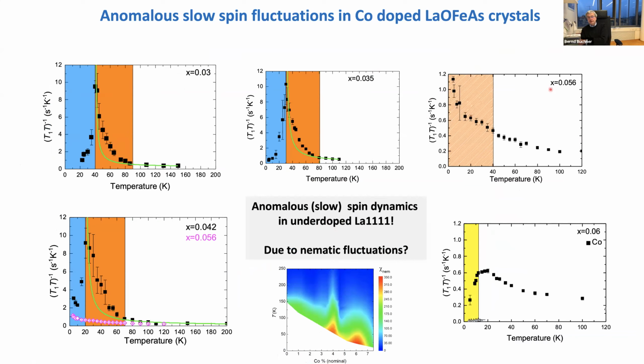That's plotted here for one of these underdoped compounds, which is hardly superconducting. And that's just a comparison with a compound which still shows magnetic order. We have this strong enhancement, this strong peak, which you expect at the magnetic ordering, and then this very unusual behavior of 1 over T1T. And this is still present in the optimally doped compounds, the compounds showing the highest Tc. Also there we have this very unusual behavior of 1 over T1T, telling you that at least this whole underdoped region is a very unusual material.